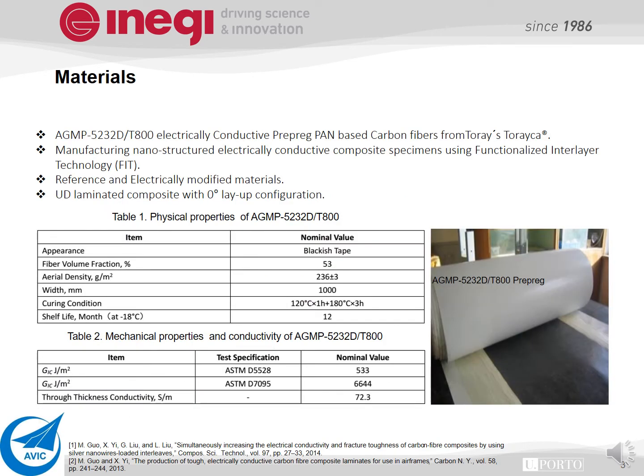The materials used for preparing the composite is AGMP 5232D T800 electrically conductive prepreg, which is a PAN-based carbon fiber from Toray. The electrically conductive specimen is manufactured by inducing the nanostructured particles using the functionalized interlayer technology. The unidirectional laminated composite with the 0-degree layup configuration are then prepared. These are the physical properties of the tape prepreg that is used in table 1, and in table 2 the mechanical properties of the prepreg are shown.